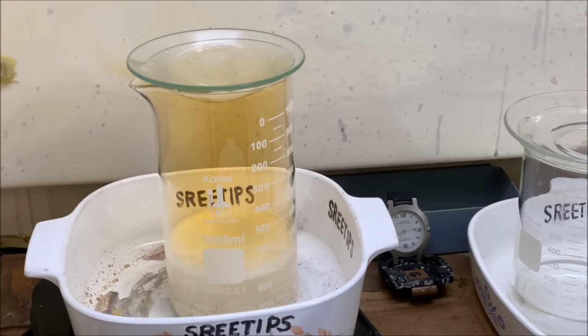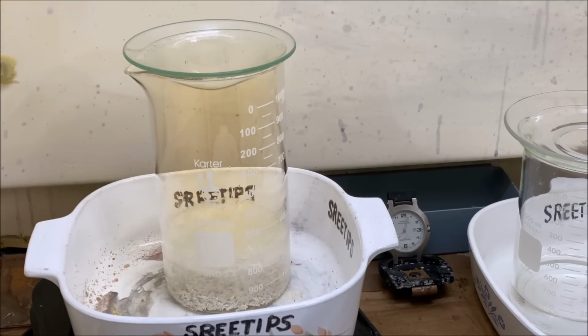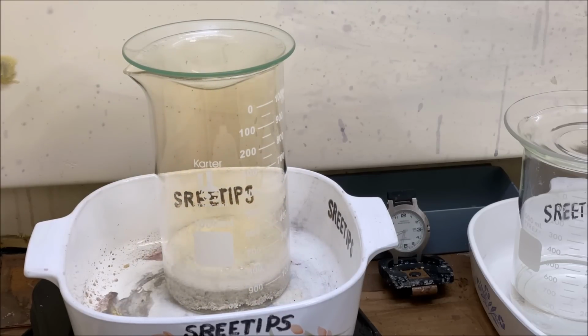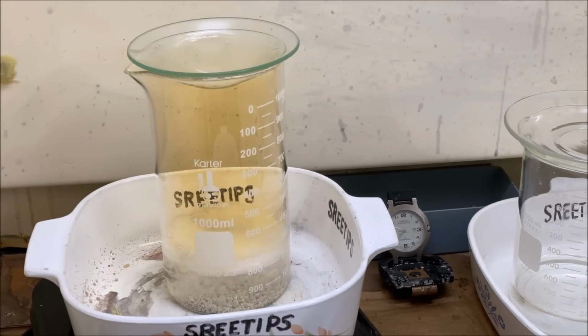In refining, we can tell a lot about the purity of our metal when we dissolve it in acid, by what color the solution is after the reaction. And if we had any copper in this pure silver crystal, then I would expect that solution to take on a bluish tint or blue color. However, if it's high purity silver, it'll be colorless with no color indication of any other kinds of metals present. Colorless liquid is what we want when we dissolve pure silver.